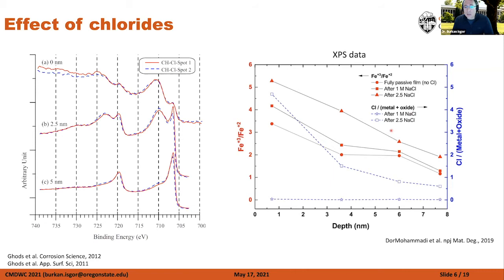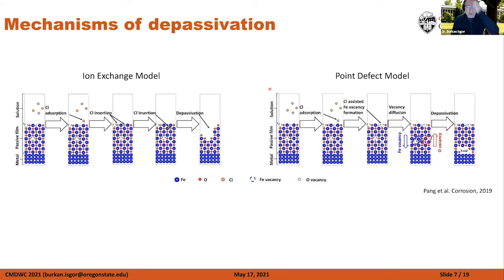So when you add chlorides, the Fe3 to Fe2 oxide ratio deep inside the passive film, near the interface between the metal and the passive film, doesn't change much, but you see that Fe3 concentration actually increases with the chloride addition. This is also something that we have seen in other people's work as well. So the Fe2 oxides basically become less dominant on the outer surfaces as chloride increases. Now, again, up to here, what I showed you has been shown by many people, so it was more like background.